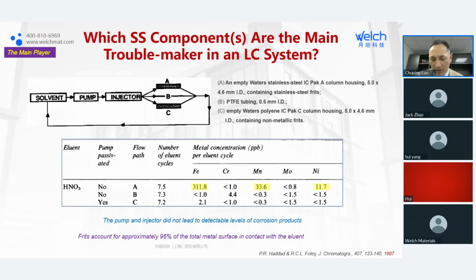This was published in 1987, so it's nearly 40 years ago. In that time the system was different from nowadays, but even then you can see the pump and injector didn't contribute to a detectable level. And it's believed there's about a 96% contribution from the frit.